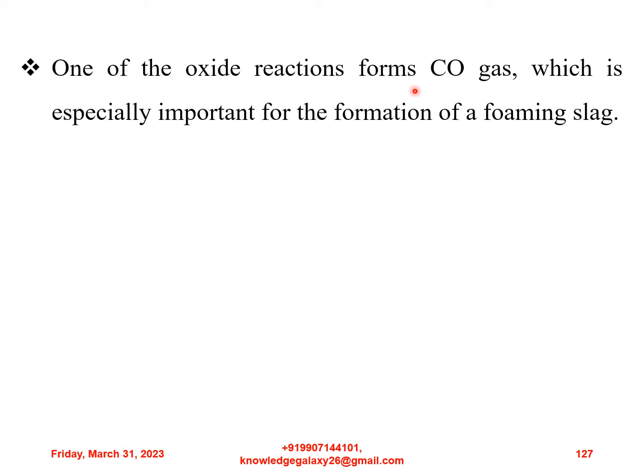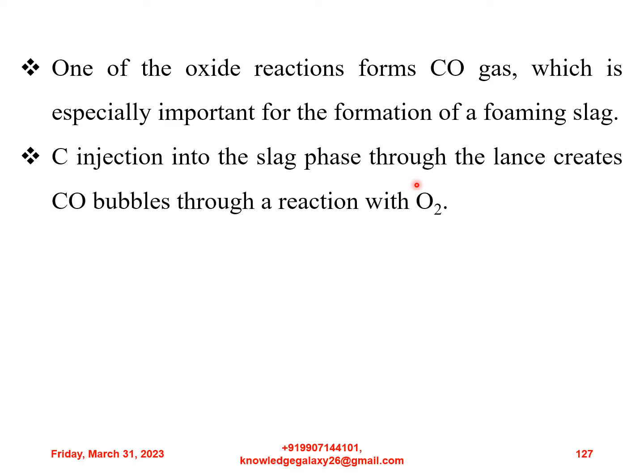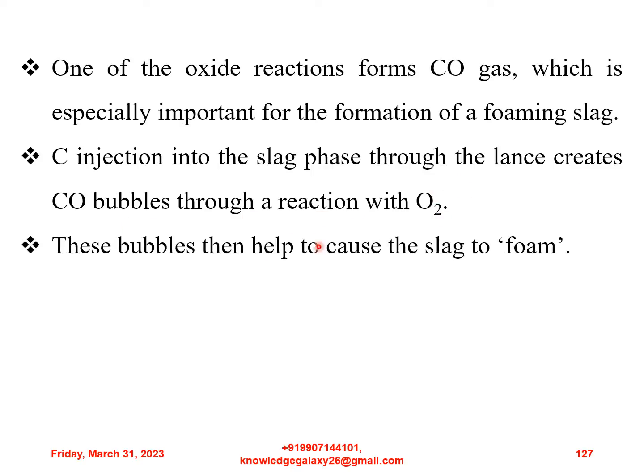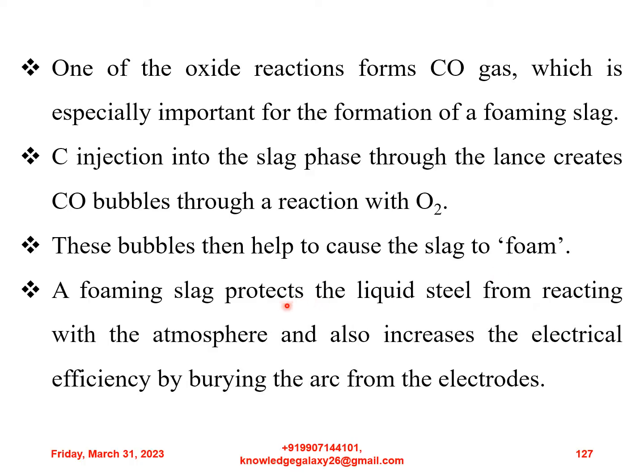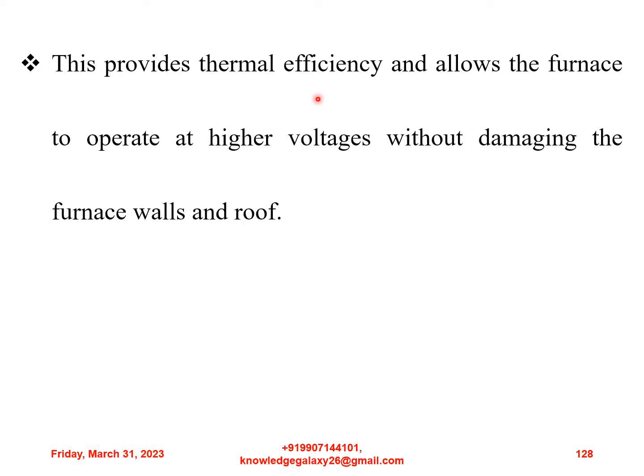One of the oxide reactions forms CO gas, which is especially important for the formation of a foaming slag. Carbon injection into the slag phase through the lances creates CO bubbles through a reaction with oxygen. These bubbles then help to cause the slag to foam. A foaming slag protects the liquid steel from reacting with the atmosphere and also increases the electrical efficiency by burying the arc from the electrodes. This provides thermal efficiency and allows the furnace to operate at higher voltages without damaging the furnace walls and roofs.